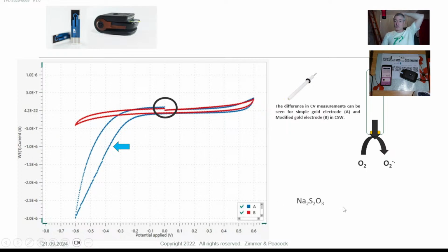If you're not sure about that, get some sodium sulfite, which is known as an oxygen scavenger. It will react with oxygen. So you put some crystals into your solution, and it'll react with oxygen. This signal will decrease depending on how much sodium sulfite you put in there. And that will tell you that you truly are looking at the signal for oxygen, because you're forming sodium sulfate and essentially scavenging or mopping up the oxygen.